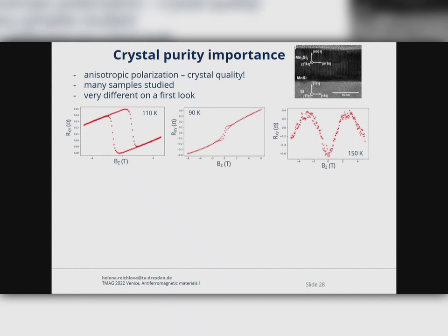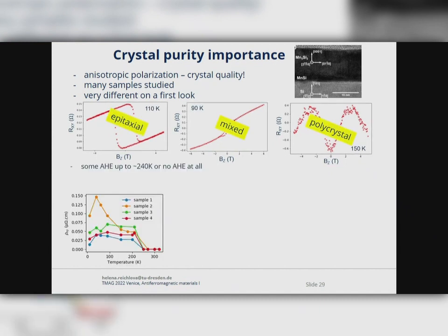On first look, sometimes you have a robust anomalous Hall effect. Sometimes it's not so clear, and sometimes it's completely absent. And this can be very accurately correlated with the phase purity of our samples. When we have the Mn5Si3 as ordered as we can make it, it gives the best signal. And we studied it systematically on one sample series, changing the ratio of the Mn5Si3 and a spurious phase.